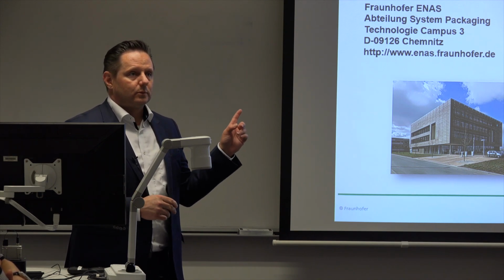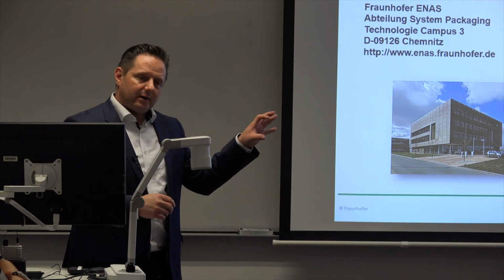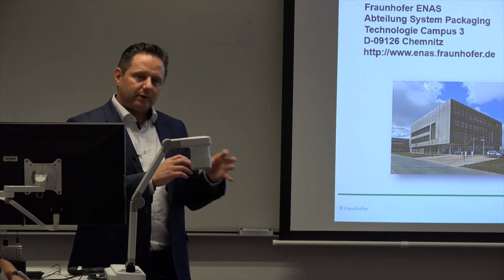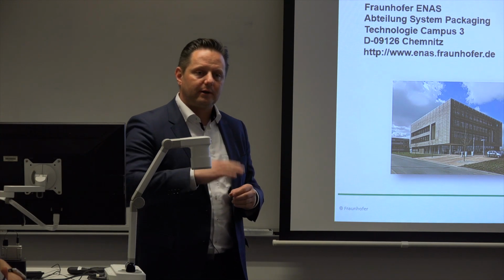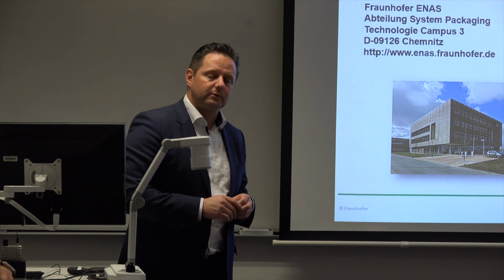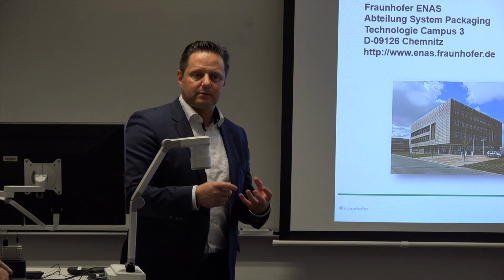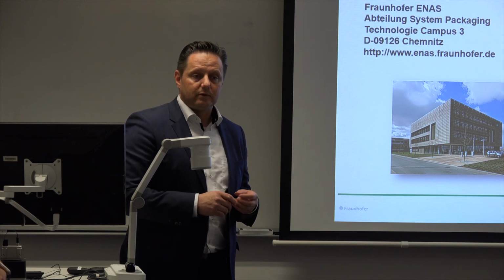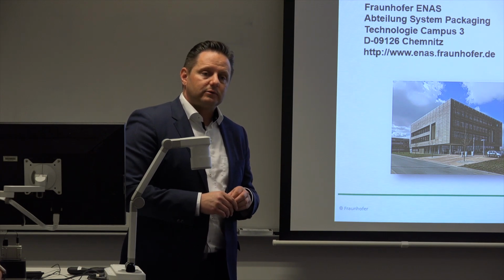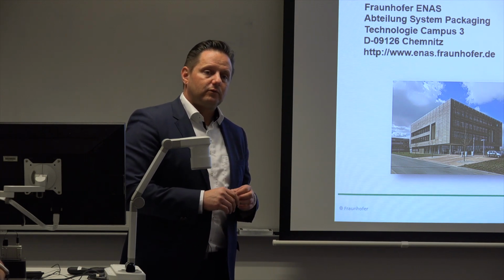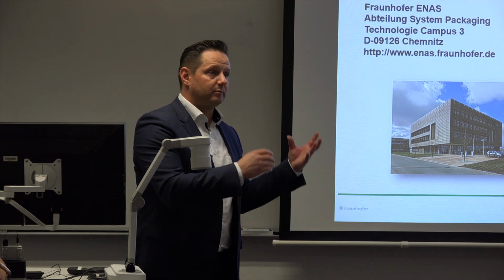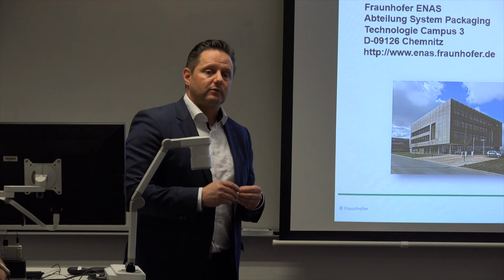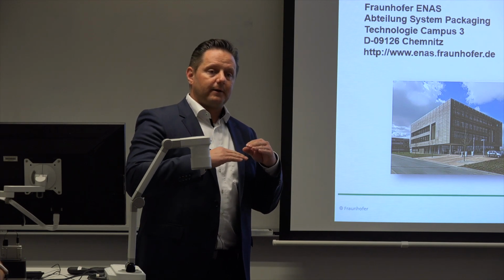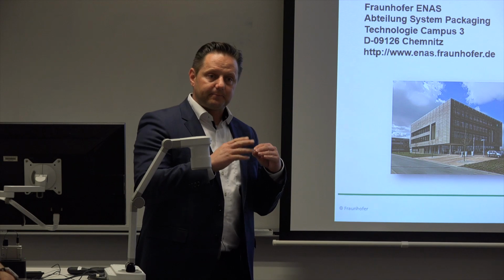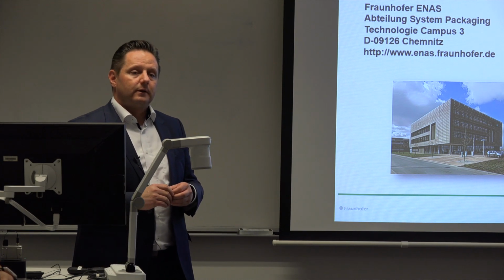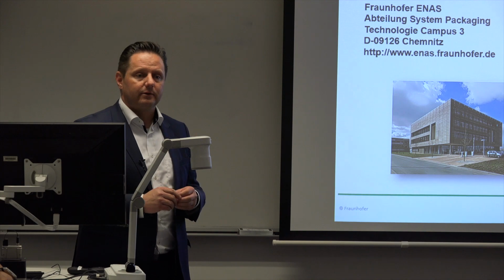And there is also another application coming up with this kind of CMUT, because there are some drawbacks because of the high voltage you have to apply to keep it excited and to keep it in frequency. That is the so-called PMUT, using piezoelectric thin film layers. There's a technology using aluminum nitride we use for activation of these membranes, but not only the membranes. I did not show the examples of micromirrors, where we have this kind of actuation of a mirror plate by using aluminum nitride as a thin film layer.